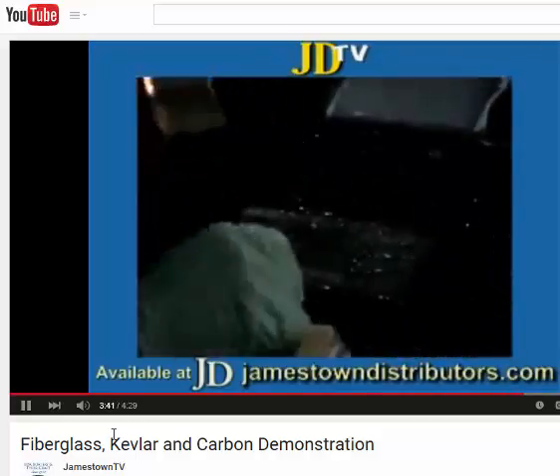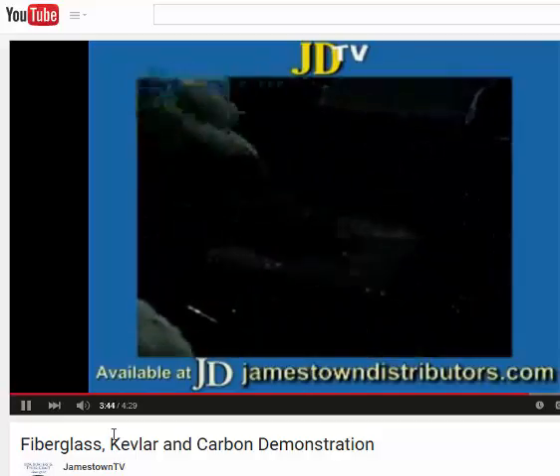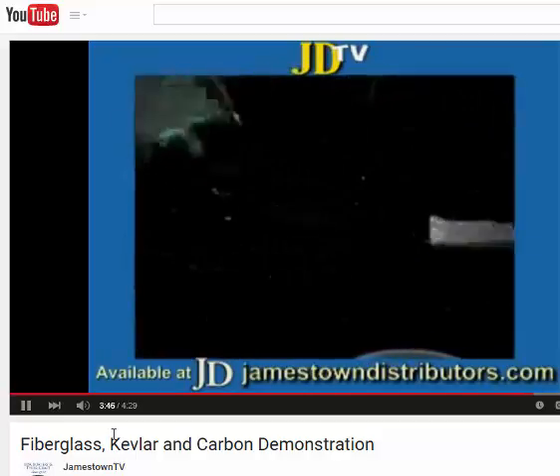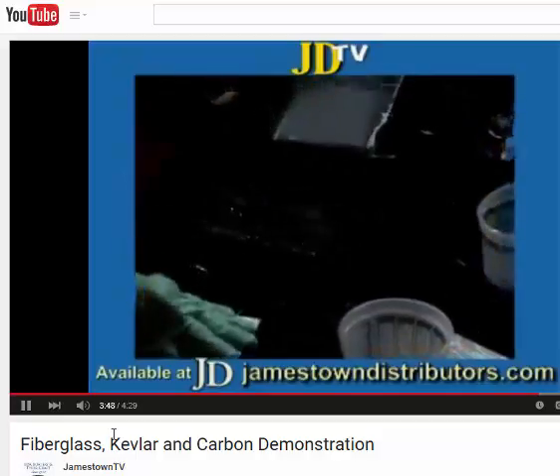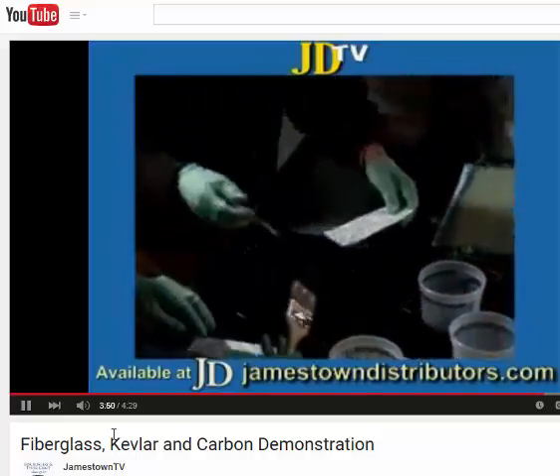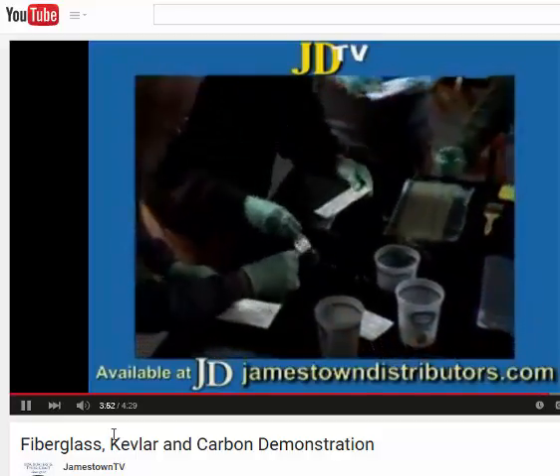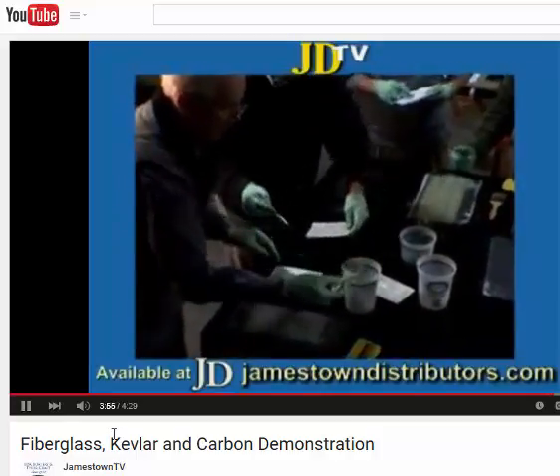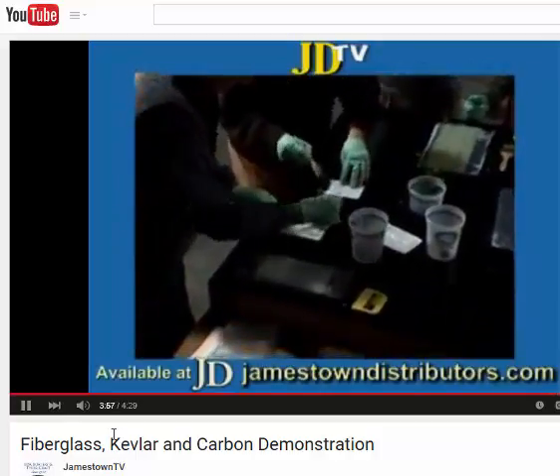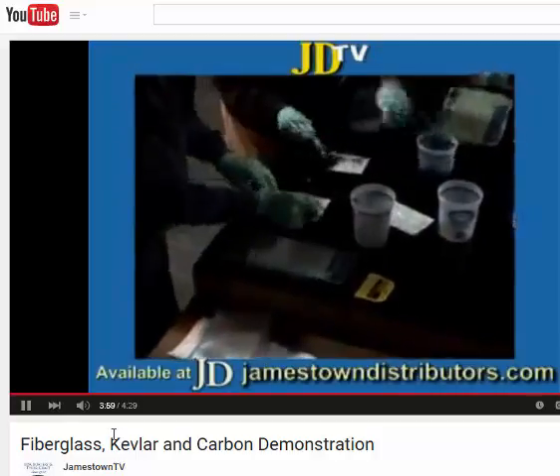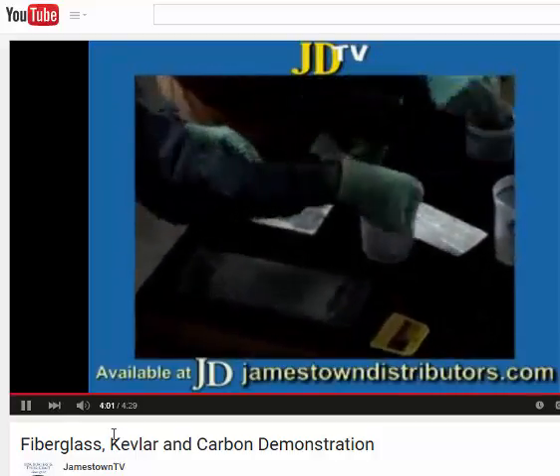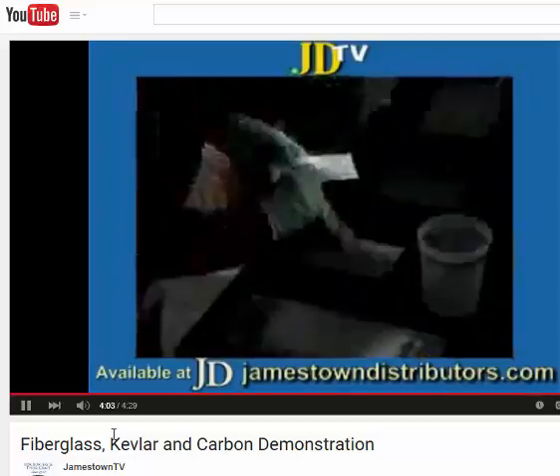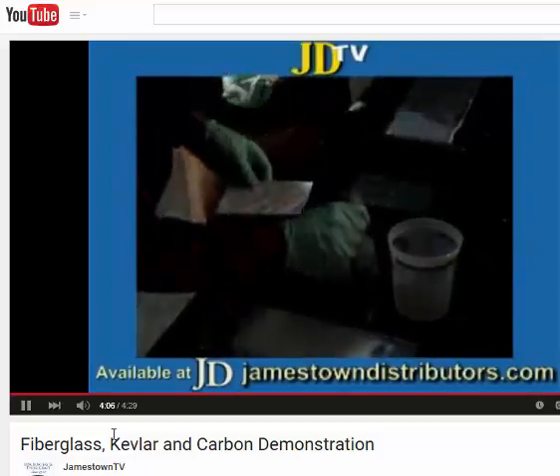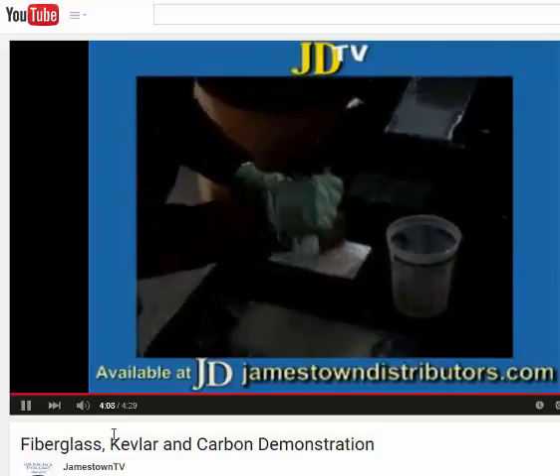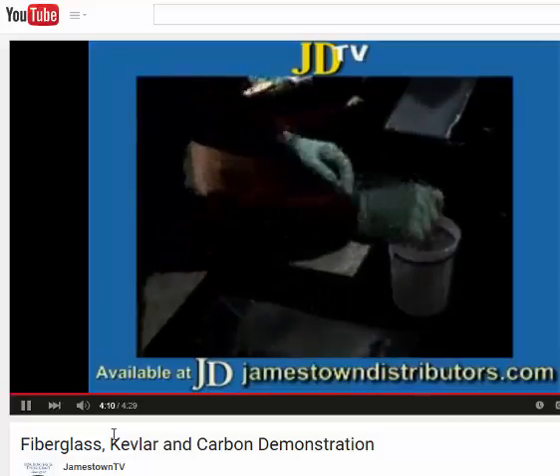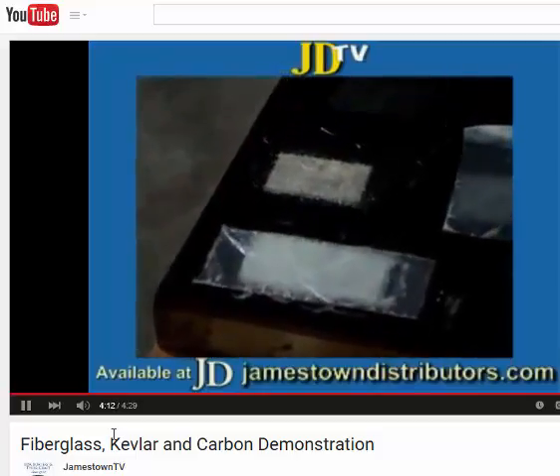You can see how the mat just really disappears with styrene-based resins. It's just really, really clear. The binder that's holding the mat together is designed to dissolve in styrene. And the problem, or the good news, is that epoxy has no styrene in it. So we put that on here, we're doing these side by side, and you'll really see how one just wets right out, and the other one doesn't. See, it looks like it's dry, but it's not. There's plenty of resin. It's just not breaking down the binder. Anyway, that's pretty much it, I think.